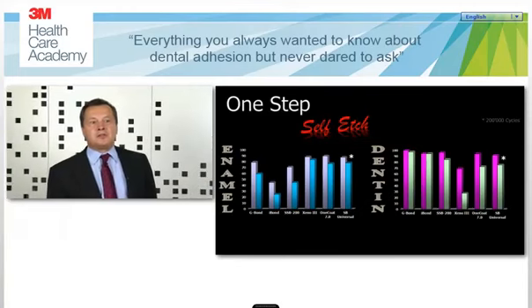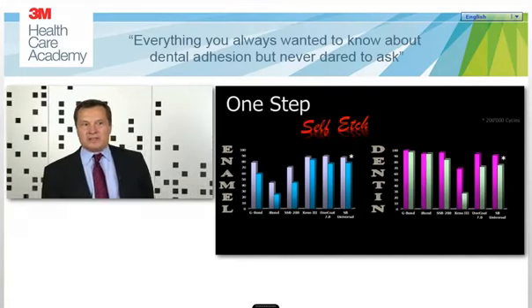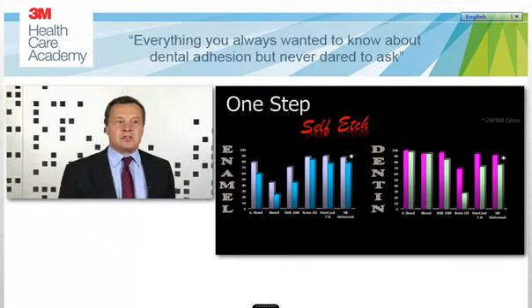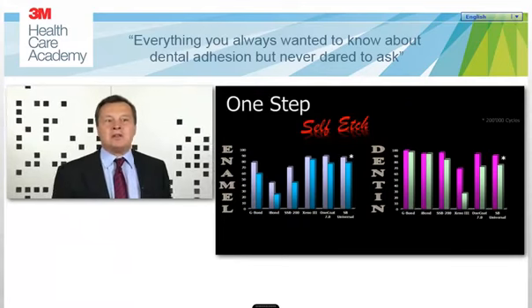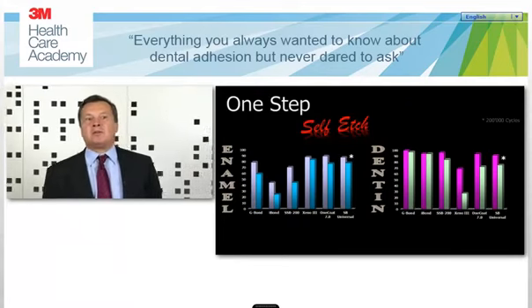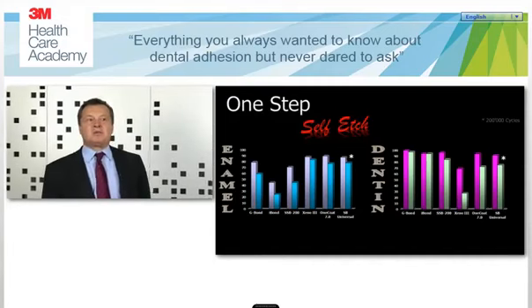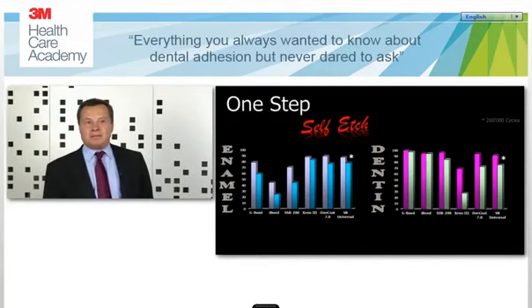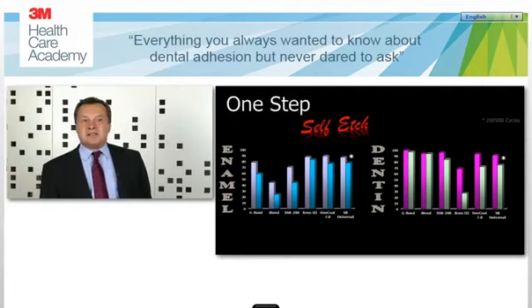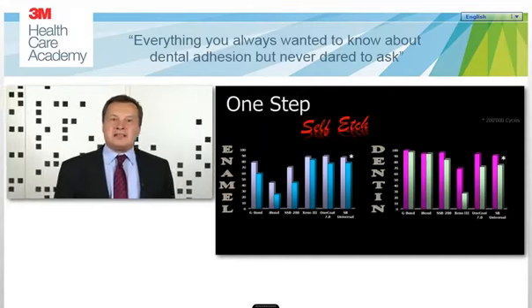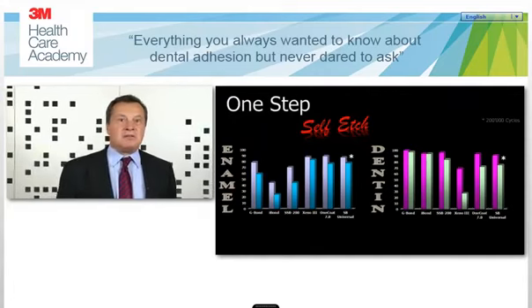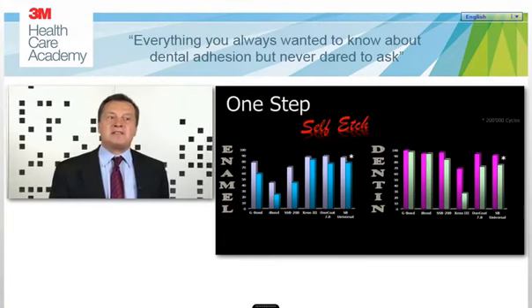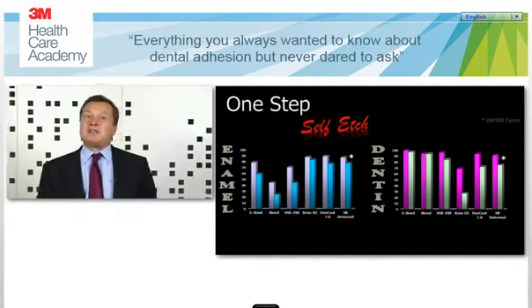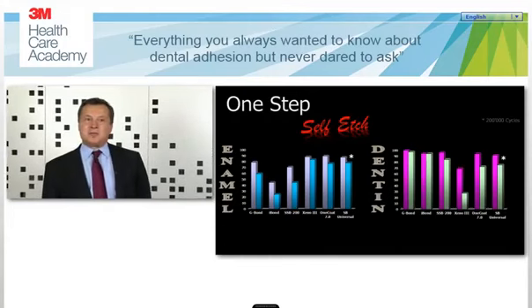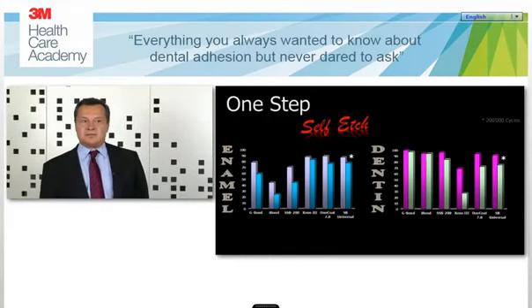If I focus on the first version of iBond, it is not the actual version, it is the first version which came out some years ago. You can see that iBond is very performant on dentin, but it is quite weak on enamel. The most obvious reason is that apparently the acid used in this product was very, very weak, so it was not aggressive enough to condition enamel properly, but because it was not very aggressive, it was possible to establish a very good dentin adhesion.